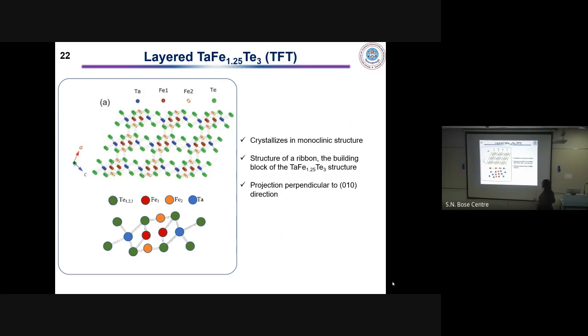It crystallizes in a monoclinic structure and comprises a mixed metal network of tantalum and Fe, and moreover there is a second, partially occupied Fe2 atom that sits in the interstitial sites. So it has a very interesting crystal structure, and the key feature is that it is antiferromagnetic with a transition temperature of around 200 Kelvin.